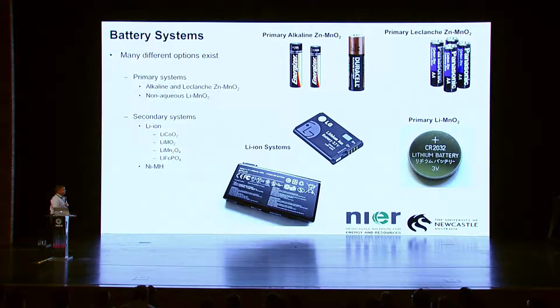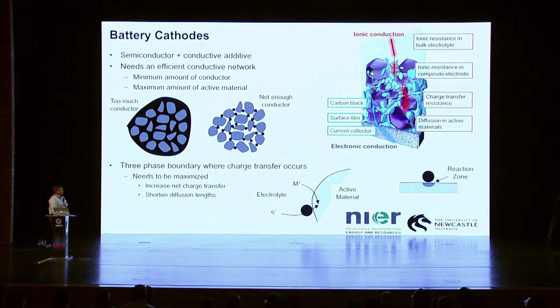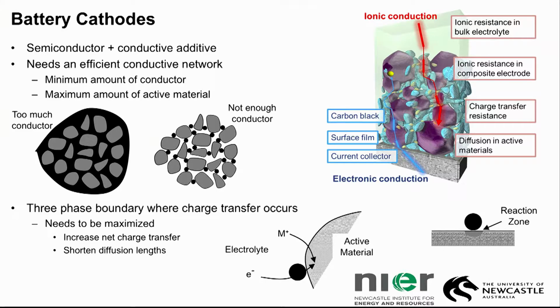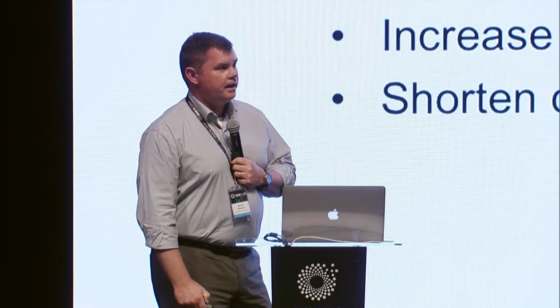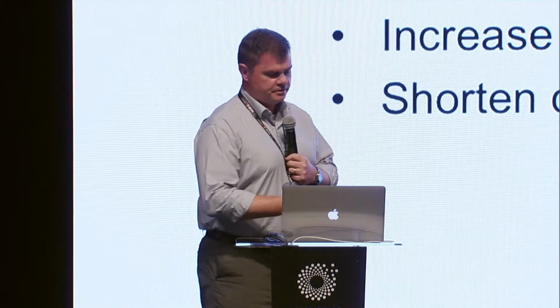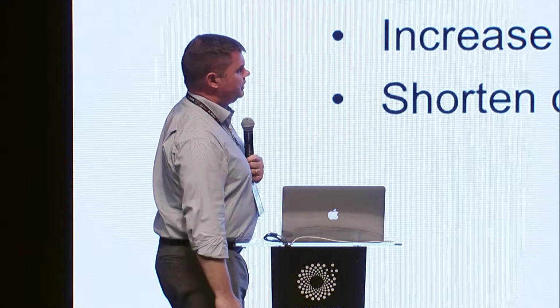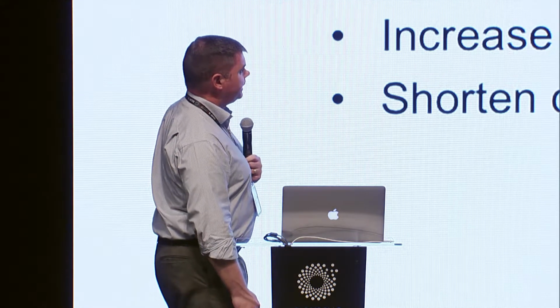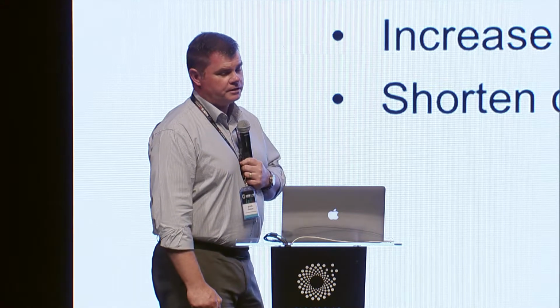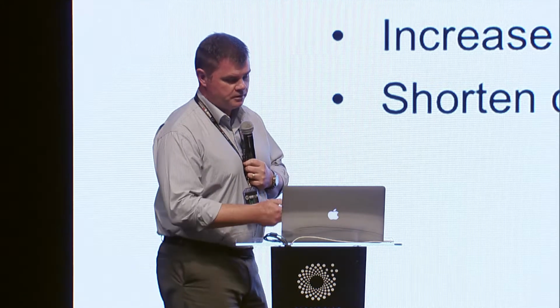All right. So one thing that we do need to be aware of when we use a battery system, for example, is that a lot of the active materials that we use are actually semiconducting in nature, particularly on the cathode side of systems. And so, of course, what we need to include there is a conductive element. And most often these days it's done with a graphite or an activated carbon or a carbon black material to improve the conductivity of these cathode-based systems.